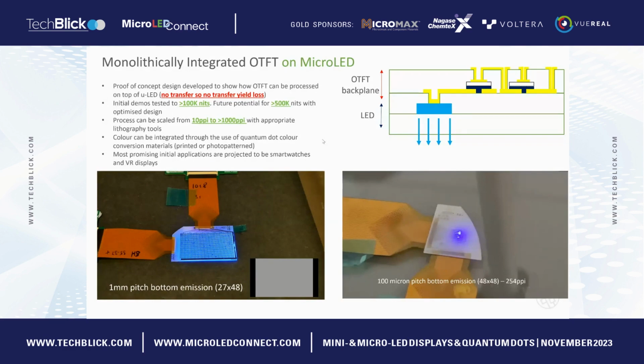So if we did a top emission device, then we could put a color conversion material straight on top of it. If we wanted to do a bottom emission device, then probably we'd have to remove it from the sapphire wafer or remove it from the transfer sheet first, and then do some post processing to put the color conversion materials on to make color. I think that's quite an attractive way of making the color, rather than having to sort the red, green, blue separately. The less you can do in the transfer process, the less complicated that part, and the more you can do with lithography, then probably the better for making color.